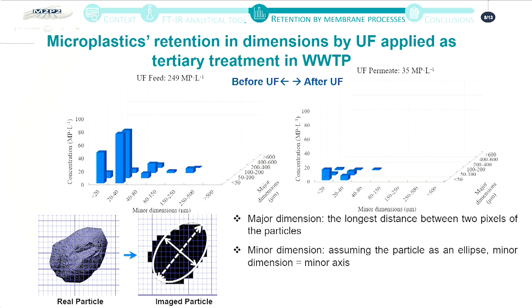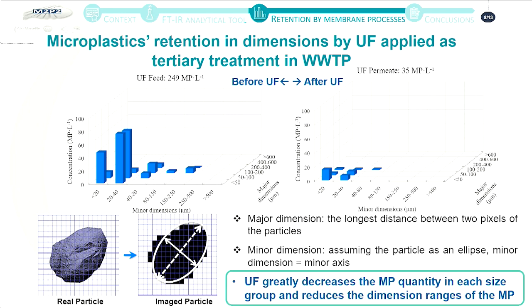So you can see on these two graphs the minor and the major dimensions, and the concentration in each of these dimension ranges. What we can see is that UF can decrease the microplastic quantity in each size group, but it also reduces the dimension ranges of the remaining microplastic particles. But still, we have microplastic with a size higher than the pore size of the membrane. Here we can assume a possible contamination of the permeate by the pilot plant and the pipes, which are all made of plastics.